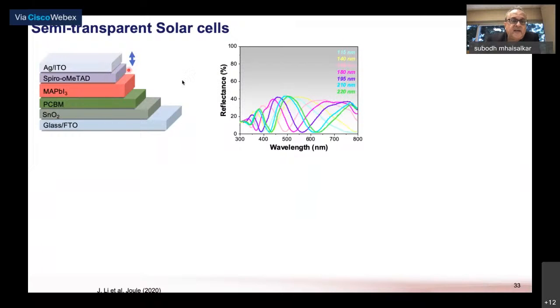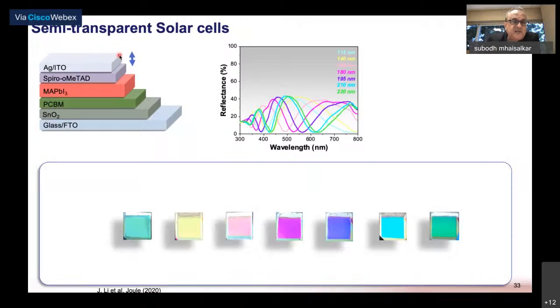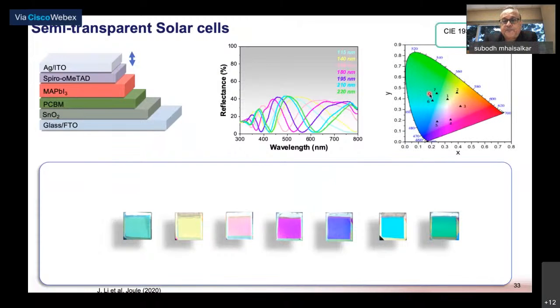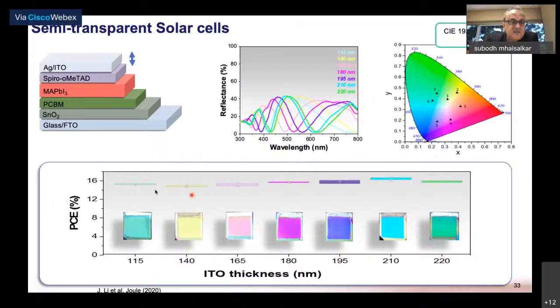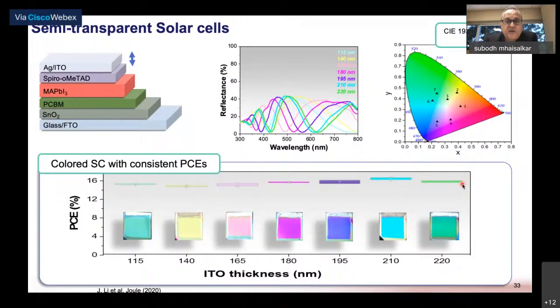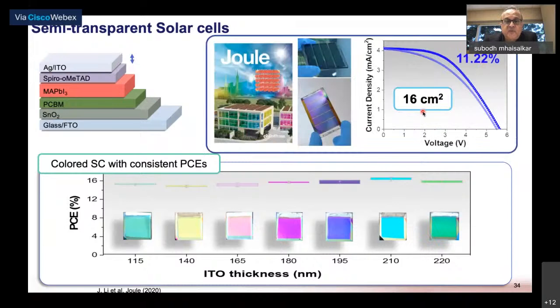And what we noticed, not entirely unexpectedly, is that the reflectance of this stack would change. And very interestingly, by changing the thickness of the ITO, we could also generate colors that could start with a light green all the way to a darker green, cyan, pink, and everything in between. If you put these colors on a CIE map, you really can see that you can control the color of this glass extremely well, and that you can do that by changing the thickness without compromising the efficiency of these devices. So the efficiencies of these colored solar cells were maintained in the range of 11.22%, even when we started making mini modules of the size of 16 centimeters square. And this would be very appealing from a building integrated photovoltaics perspective, that you can get a gamut of colors by controlling the thickness of the individual layers.